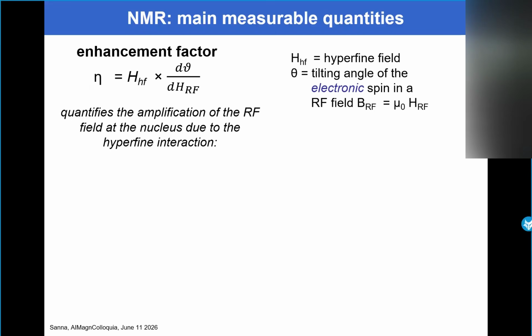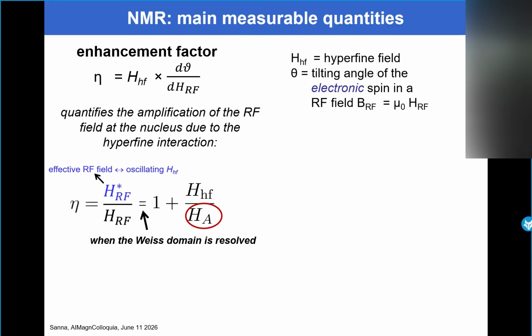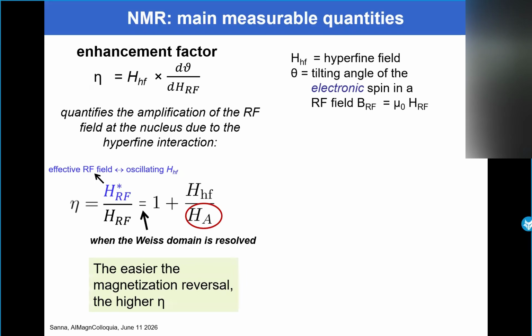But what is important is that this parameter, which can be operatively also defined in this way, is higher when the electronic magnetization can be moved, let's say, more easily. So the easier the magnetization reversal, the higher this enhancement factor. What does it mean? It means that you have a soft material.